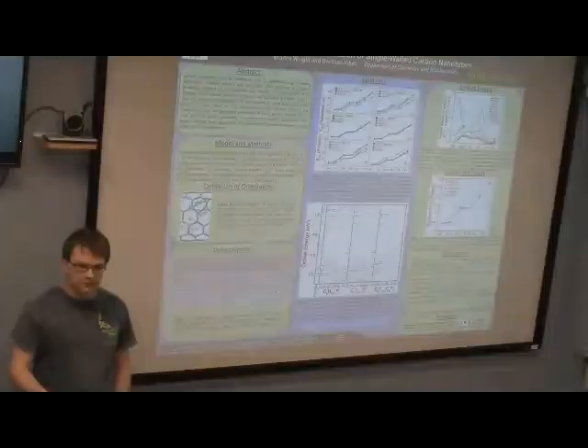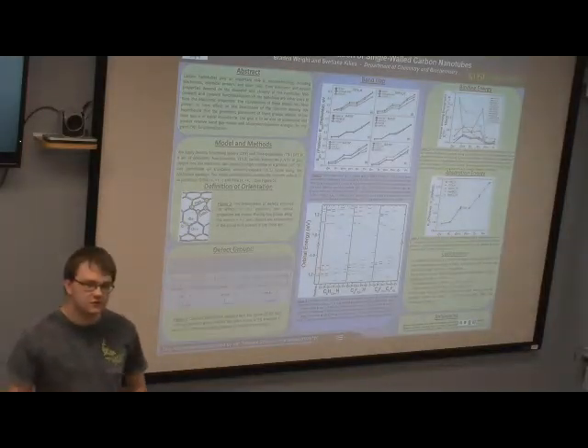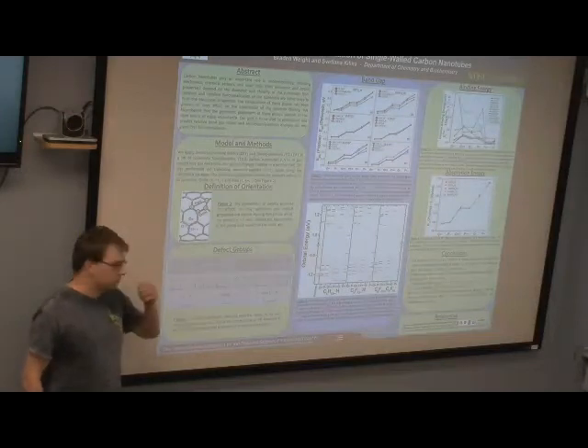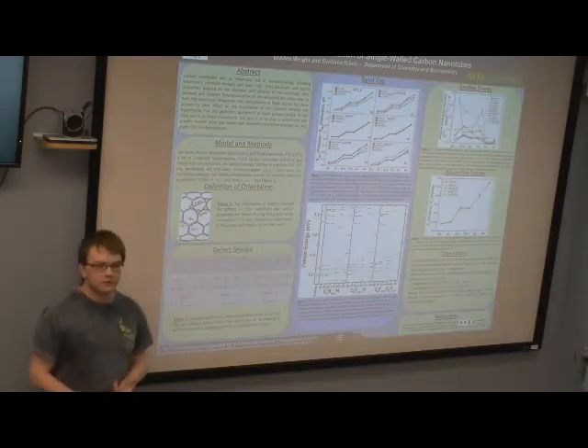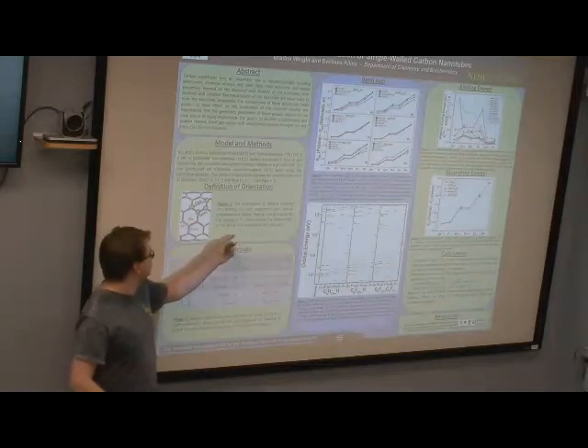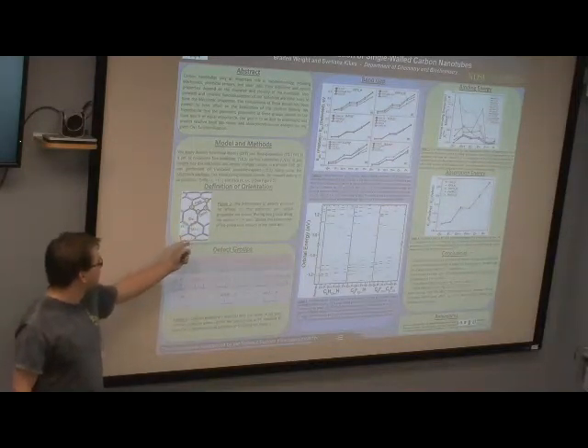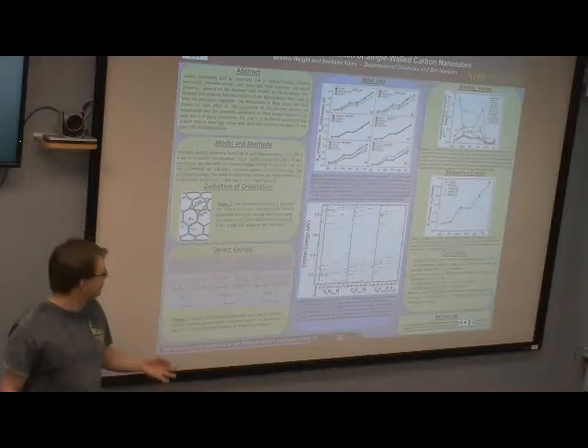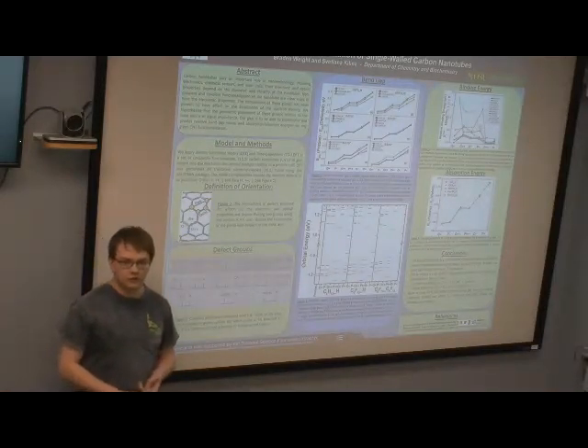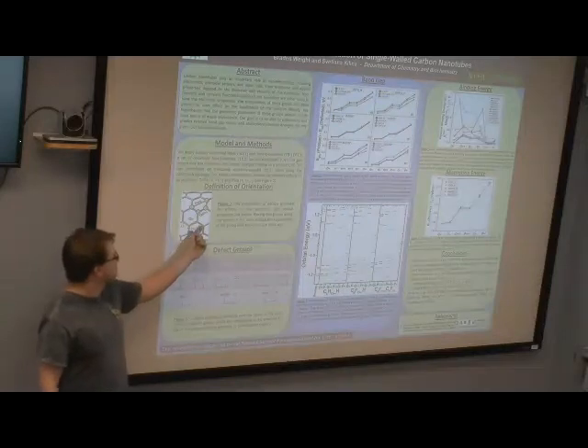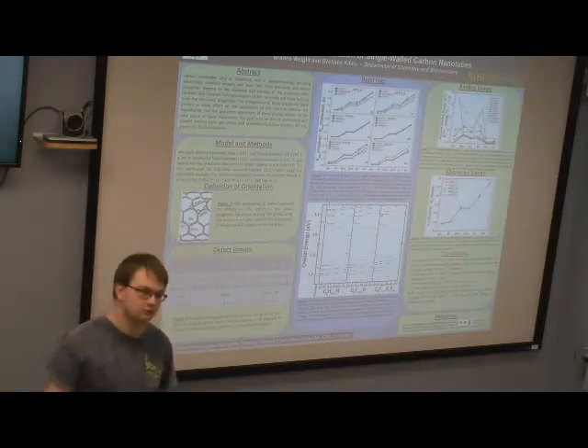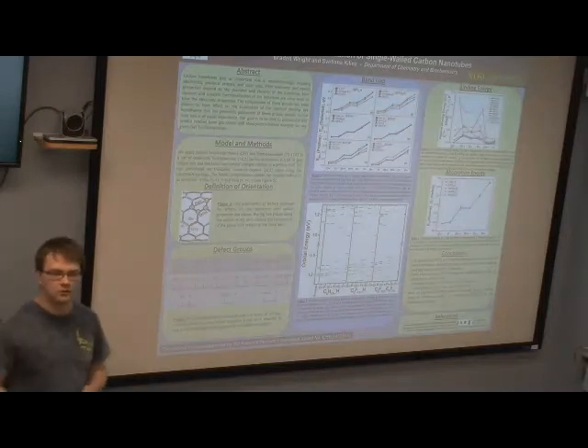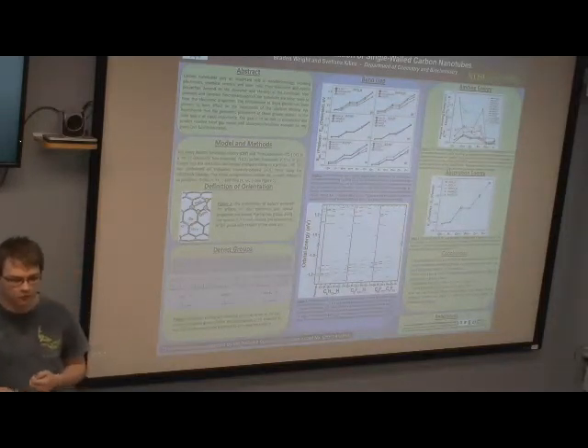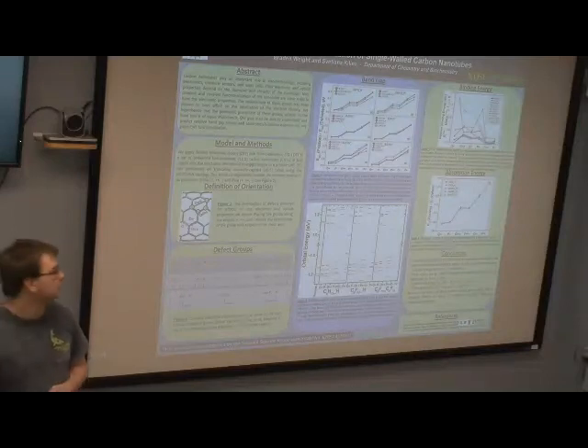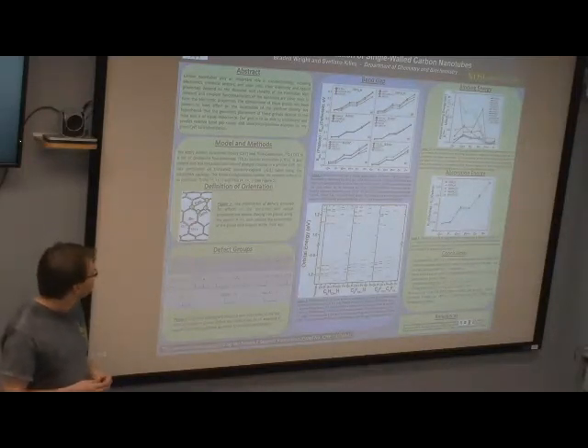And we'll also do this with different groups, but we'll also do it in different orientations. As you can see here, we denote three vectors, the plus, plus, and the minus directions, shown by the red, the green, and the blue arrows. So we can define them also as ortho and para. So you can go adjacent or across the ring. And it has been shown if you jump farther than one ring, the absorption and emission properties die off very quickly, the farther away the defects are from each other.